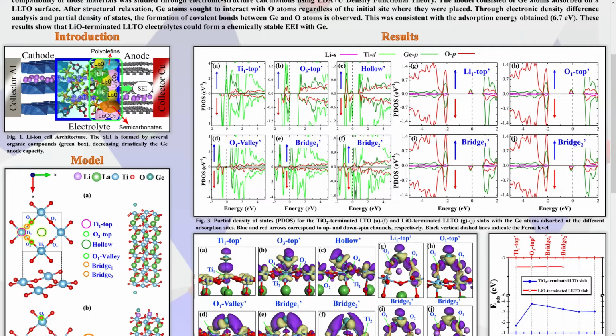Results. As can be seen in Figure 3, the covalence is confirmed by the partial density of the electronic states of the first monolayer with adsorbed germanium. From A to F, for the case of the titanium dioxide termination, there is strong hybridization between the germanium p and titanium d orbitals at the titanium top site.